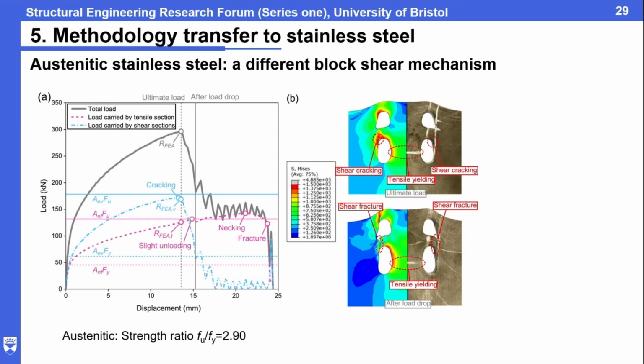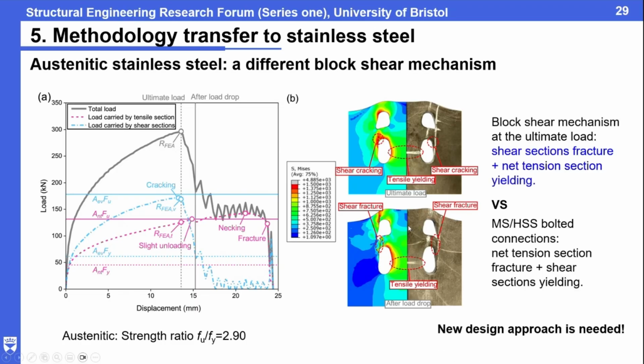However, when we transfer to the austenitic, we found that it seems different. For the austenitic, the strain hardening is very significant when the net section's strength develops and hardens, so the shear plane actually has much more time to develop its shear strength. The interesting finding is that for the austenitic stainless steel bolted connection, the fracture first occurs along the shear plane, not the net section area. So this is a very interesting finding. It means the design equation for the austenitic stainless steel bolted connection needs to be totally refined. This is another work we have recently published. We also propose a different equation based on the failure mechanism we observed.